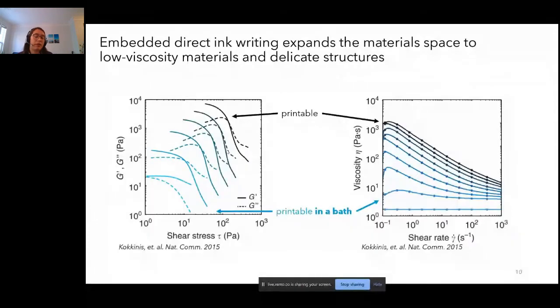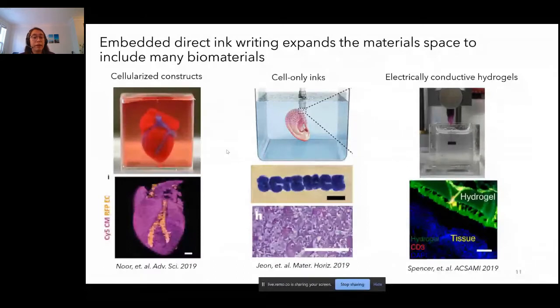What this means is those blue inks, those low viscosity inks, are now going to be printable as long as we use a support bath. People have been able to print a wide variety of materials using this technique before, and it's been particularly useful for bioprinting. You might have seen this paper a couple of years ago where they printed a heart, which actually included human heart cells, as well as some extracellular matrix. You can print these cellularized constructs and actually use the bath to support the growth of that construct by introducing nutrients that'll feed the cells and allow the cells to proliferate.